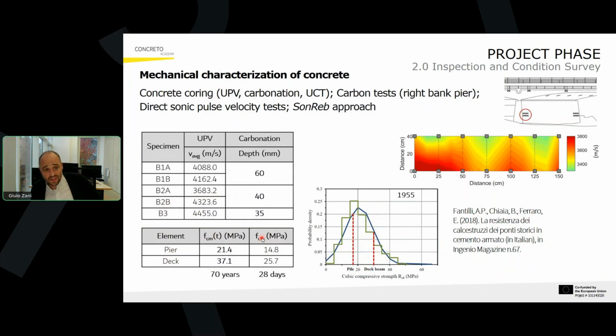In the assessment phase, we had the possibility to carry out some mechanical characterization tests on concrete. In particular, as you can see here, we carried out some coring, over which we measured the ultrasonic pulse velocity, and we also have a measure of carbonation. So the carbonation front is pretty deep, 60 millimeters, 35 millimeters, depending on the porosity of different materials. But what is interesting is that besides the homogeneity, which was measured by means of ultrasonic and sonic transparency tests, we were able to obtain some information from the coring.